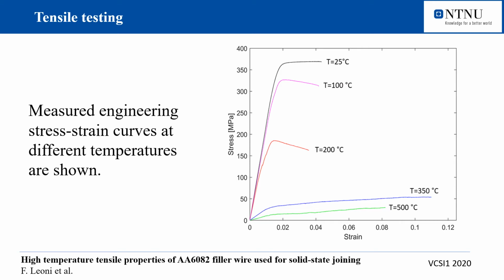The measured engineering stress strain curves at different temperatures are shown here in the figure. As expected, the softening of the aluminum alloy starts already at very low temperatures. The strength then continues to drop with increasing temperatures. At 500 degrees, the UTS is as low as 24 megapascal.